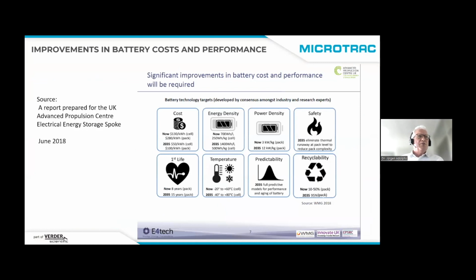So the improvements in battery costs and performance is an older report from 2018, but it's still valid, I would say, because the costs of batteries should be reduced remarkably from about $130 per kilowatt hour per cell down to about $50 in 2035. The energy density should be doubled at the same time, power density by a factor of 4. Of course, safety is an issue, recyclability, temperature, and first life issues.